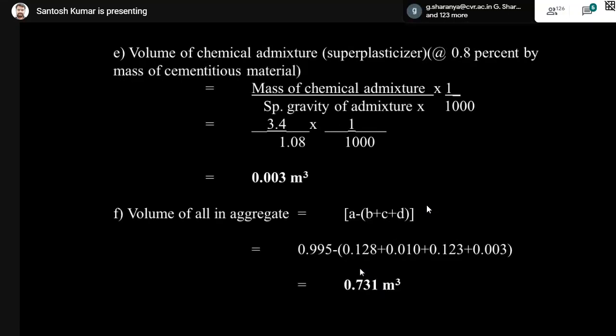When it comes to the chemical admixture, we are taking 0.8 percentage, but practically polycarboxylate ethers can be designed at 0.4 percentage only. But this example is in the standard, so I have taken 0.8, but 0.4 is more than enough when it comes to present-day polycarboxylate ether based admixtures. So the mass of this chemical admixture is 3.4 kg of total cementitious content. So 3.4 divided by specific gravity of admixture, 1.08, the volume of chemical admixture is 0.003 cubic meter.